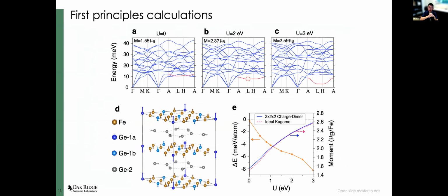One way you can solve the structure is sort of difficult because of the bigger superlattice. The other way is to go back to DFT calculation and ask, if you relax your lattice structure, what might the stable structure be? So we did a DFT plus U calculation, and you actually find that if you increase U, the lattice tends to become unstable, moving towards a CDW phase. So the main driving force is really the local magnetic moment. If you have a larger local magnetic moment, it looks like the system does not want to maintain the Kagome structure.